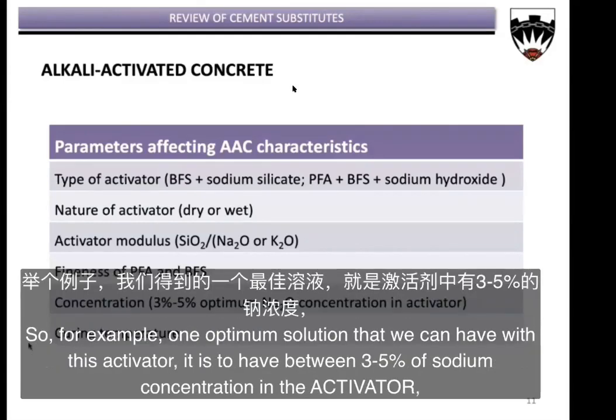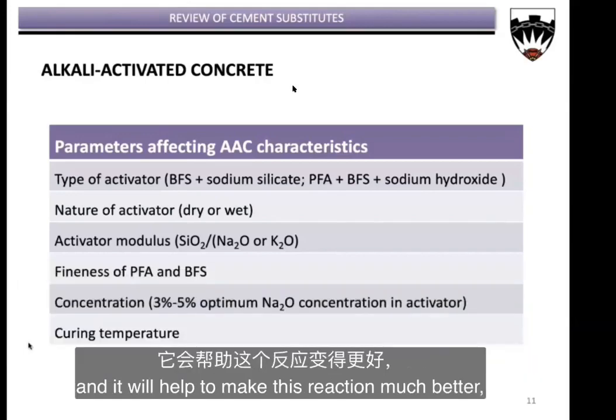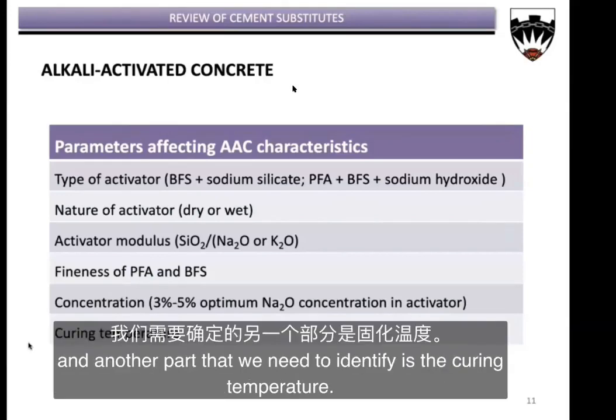So for example, one optimum solution that we can have with this activator is to have between 3 and 5% of sodium concentration in the activator, and it will help to make this combination, this reaction, much better. And another parameter that we need to identify is the curing temperature.